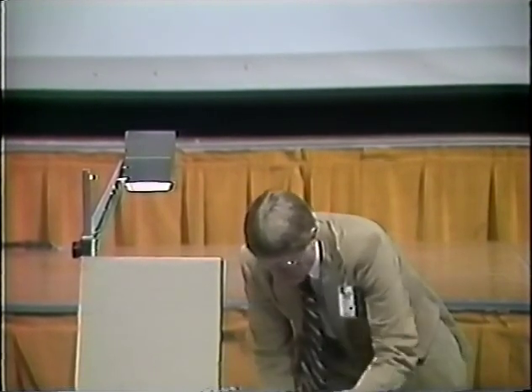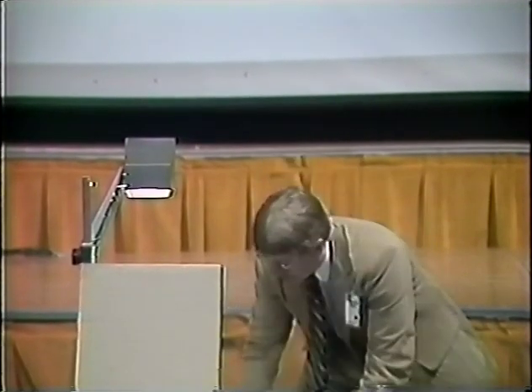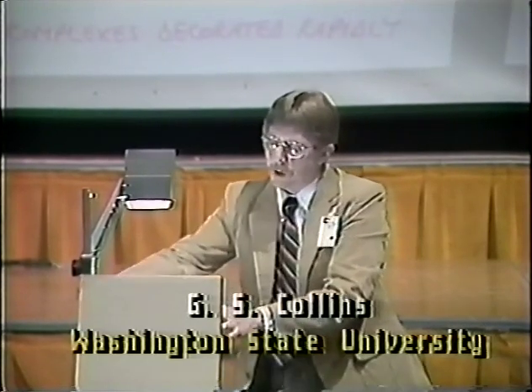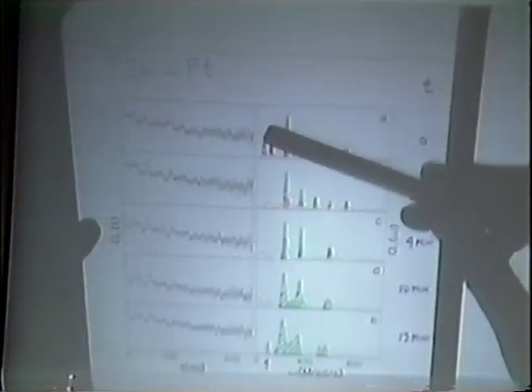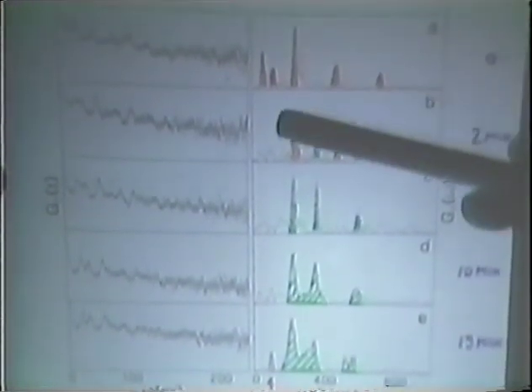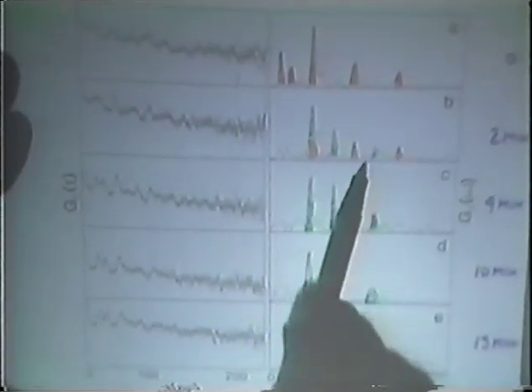Okay. Because time is going, I'm going to skip. Well, let me just show very briefly what happens when you introduce hydrogen into platinum metal. Here in the top of the figure is shown the signal for two different vacancy complexes in platinum. The one with the higher frequencies, shown by orange, is a divacancy complex. And if you use an electrolytic bath, you charge it for 2 minutes, you convert about half of the orange signal to this green signal, which does not have a 1 to 2 to 3 ratio of Fourier components anymore. After 4 minutes, you've converted this entire high-frequency signal to this signal.